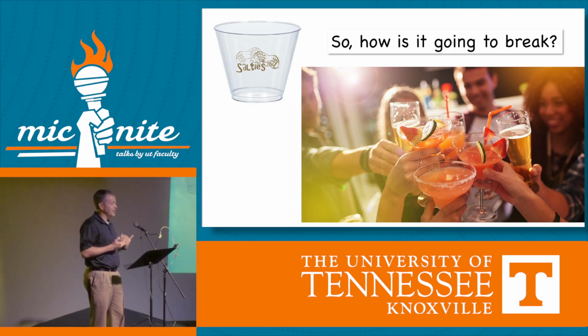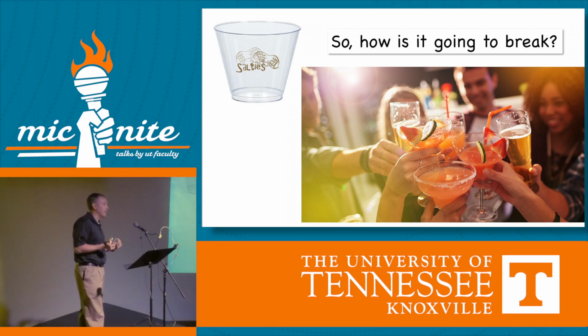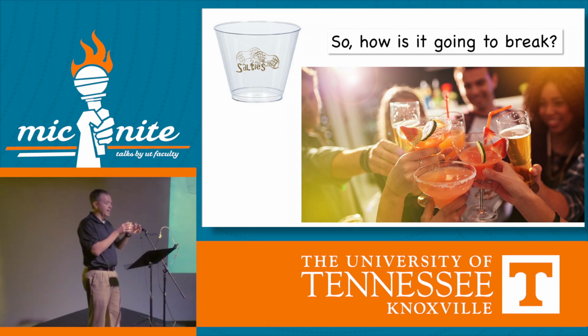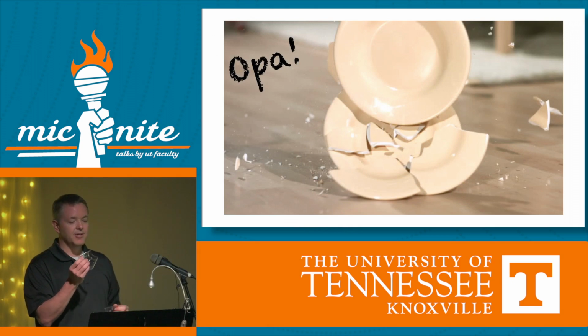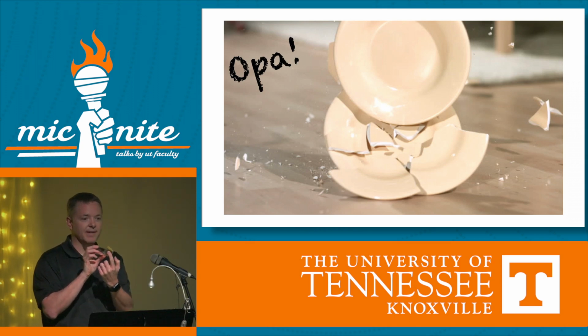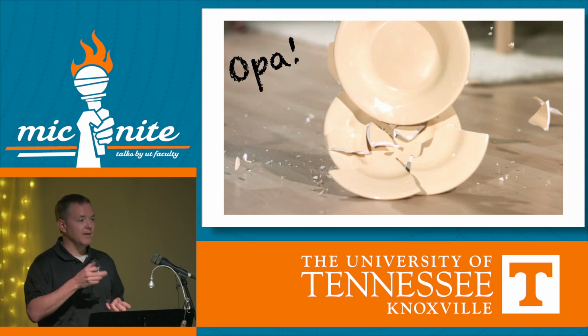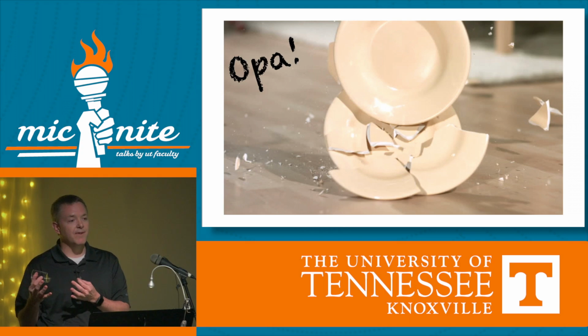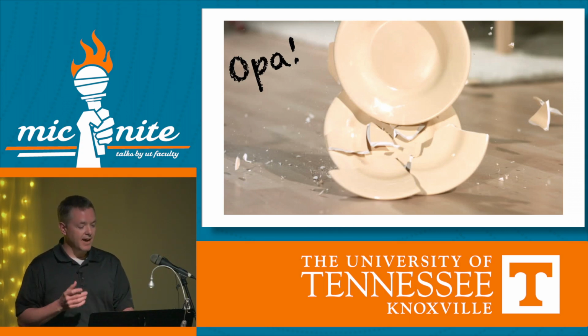Now, as mechanical engineers, it's like the best job ever because we get to break things and we get paid for it. It's awesome, okay? So if we take something simple like this and we actually break it, we should be able to put some force on it and pop that thing, and sure enough, if the folks up front can see, it goes right down the line and it goes right along that starburst pattern in the bottom and stops at the belly button, okay? Any product that you make conventionally has anisotropy based on the way it was manufactured. So we need to design for that and account for that.